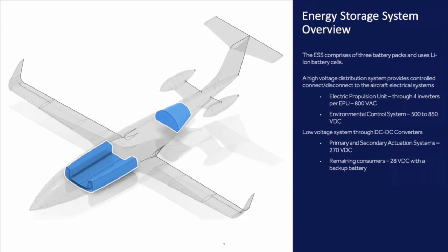The idea is that we can always rely on one of those three battery packs. They're completely redundant. Each of them can fly the plane actually quite significantly and safely. They work through a DC to DC set of converters, so some redundancy there, and they feed into a small array of smaller batteries, 28 volt and 270 volt buffers, that will give us an uninterruptible low power supply no matter what, meaning even if the high voltage somehow fails and you don't have propulsion, you will still have buffers that will allow control of the aircraft. So this is a very, very critical system, obviously, not just because it's fuel, because it feeds everything.